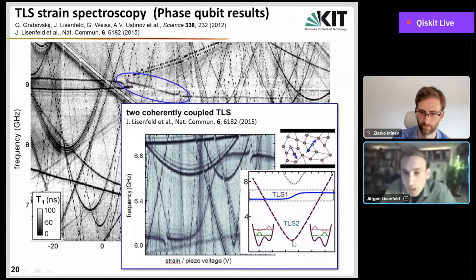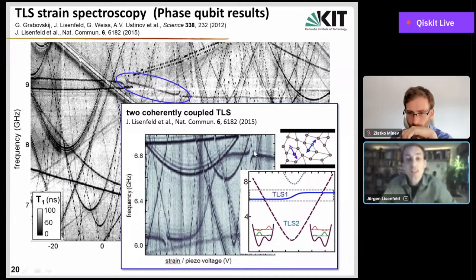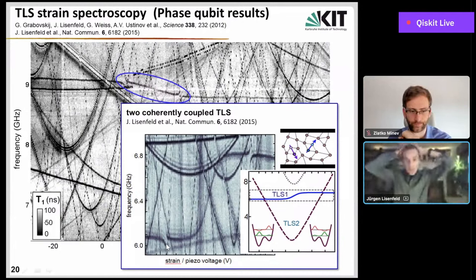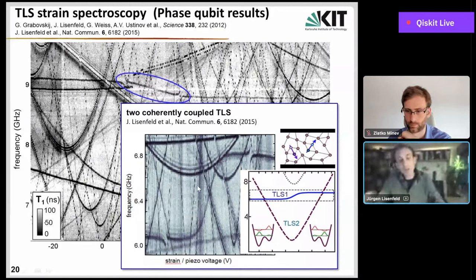And we can, of course, go further and tune TLS2 in resonance with TLS1, which happens here and there. And accordingly, we see here and there the avoided level crossings opening up, which then tell us how much exchange coupling strength we have between these two interacting defects. And so this just nicely shows that these measurements now allow us to really completely characterize and investigate even coupled defect systems, basically with access to the individual constituents. And yeah, so this just shows that these are really powerful measurements from which you can learn a lot.